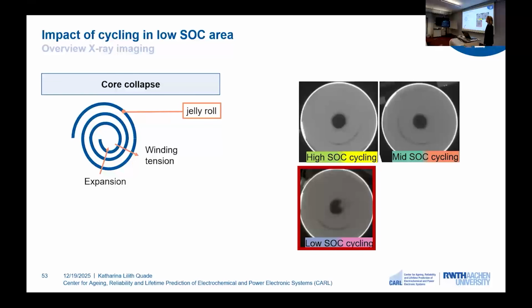Let's return to the CT images. Here on the left-hand side, you can see a very simplified schematic of the jelly roll. In the cylindrical cell, two forces are supposed to be in constant equilibrium: the winding force and the expansion force. If the expansion force increases beyond the winding force, then the jelly roll will break at its weakest point, which is the core. We can also see that this leads to a shift of the electrode layers, and this can significantly affect our capacity.